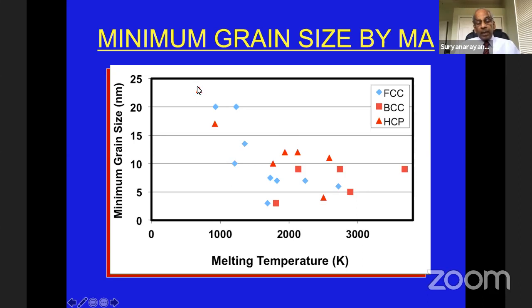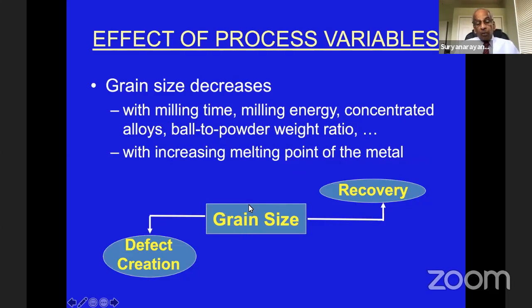And therefore, if you now look at this, with increasing melting temperature, the grain size produced decreases. That means if you have a very high melting point metal, it's possible to produce very fine grain sizes. If it's a relatively low melting point metal, the grain size is going to be large. And here, of course, we are talking about 1000 degrees Kelvin, but very low melting point metals are more difficult. If you want to determine what factors are responsible for determining the grain size, there are two things. One is defect creation. If you create more defects, it's possible to decrease the grain size. But recovery also takes place because of the heat effects, and therefore the grain size increases.